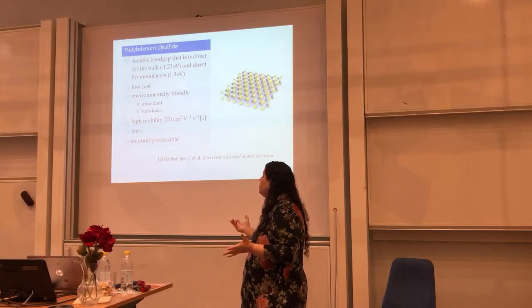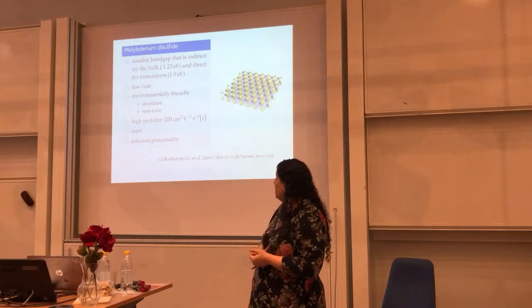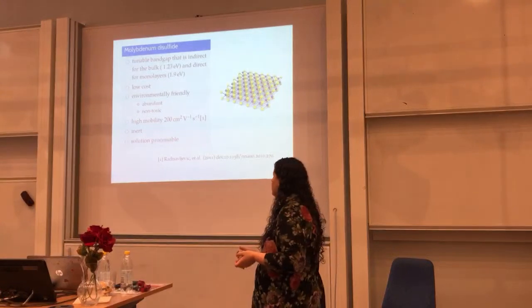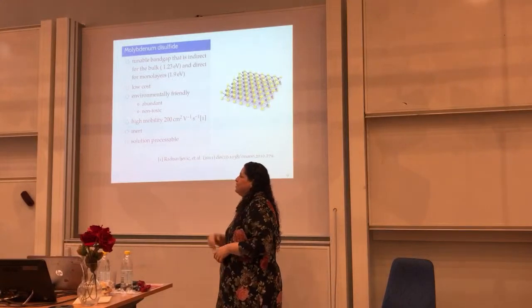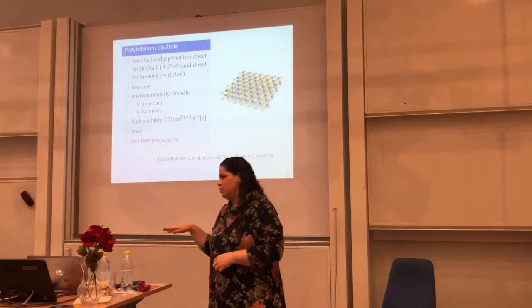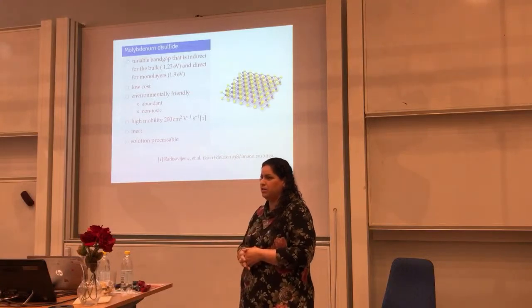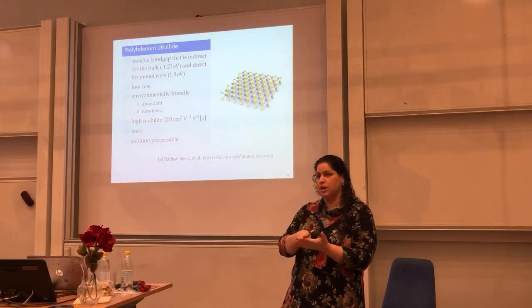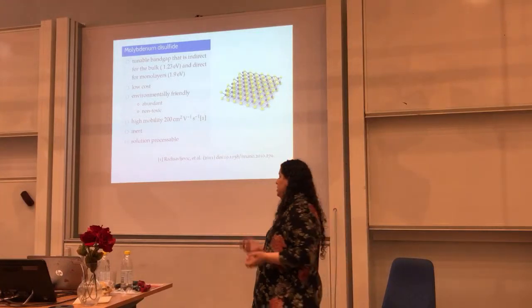Like, the band gap will change depending on the number of layers you have of the material, and will go from an indirect band gap semiconductor to a direct band gap semiconductor. Which means that if it's a direct band gap, it's like when you have to go somewhere with a plane, you don't need to make a connection. So what happens? You go faster. So you can switch this device on and off faster. That's the great thing about it. But it only happens at monolayers.